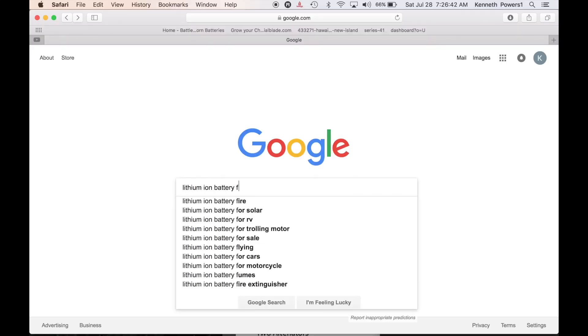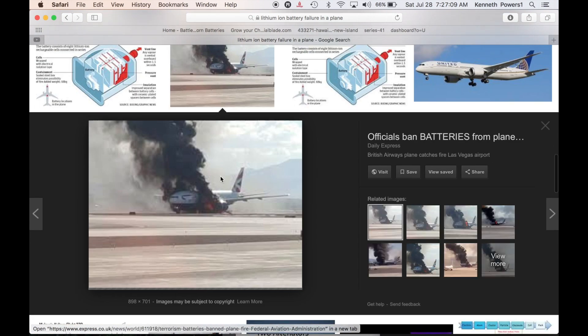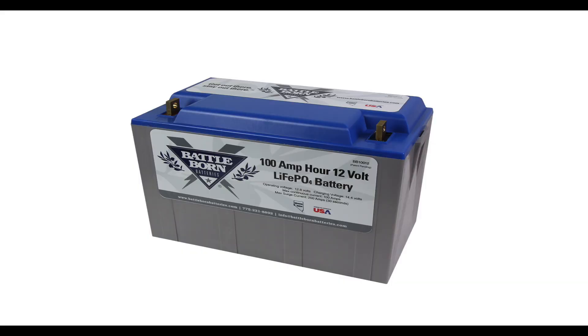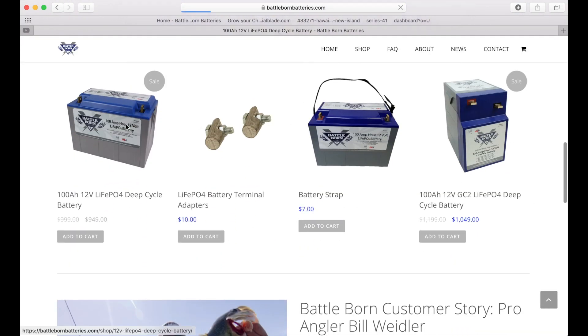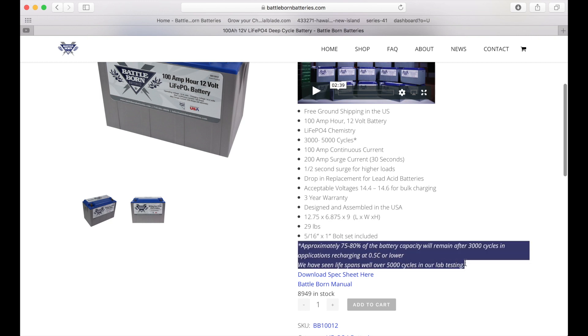Now it's time to do some real research. Why didn't I look at lithium batteries before I bought these AGM batteries? Wait — I know why. Because fire is probably the only thing that could sink Aquarius. But that was lithium-ion batteries. Let's look at lithium iron phosphate batteries. We're going to take a look at the Battle Born 100-amp-hour 12-volt battery and pull the important numbers off the website. The important numbers are: life is 3,000 to 5,000 cycles. You can cycle a lithium iron phosphate battery to 100% of the total charge. And after the life of the battery, you're still at 75 to 80% capacity.